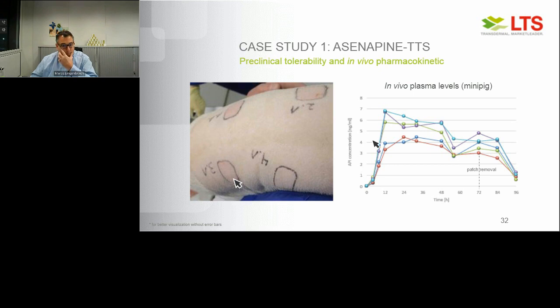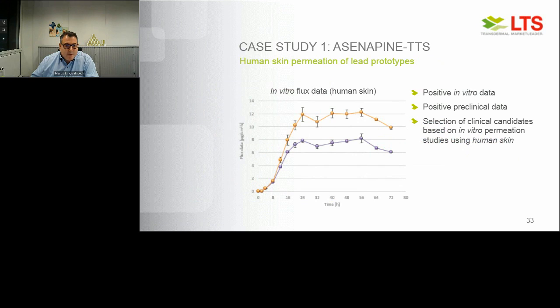And we also measure pharmacokinetic properties and to see whether we can achieve the right plasma concentration with these prototypes or not. So together, tolerability and also PK profile is then the basis for selecting the right formulation and going to the next step. Before we do that, we confirm the right clinical candidates because based on positive in vitro data, positive animal data, we can select these clinical candidates. We do this based on these in vitro studies using human skin tissue. And these are the results here of this permeation profile within 72 hours.